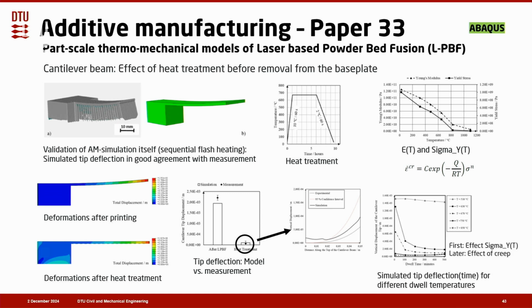So we also made a little DOE, where we simulated the tip deflection as a function of time for different dwell temperatures. Obviously, in the beginning it's the effect of the yield stress as a function of temperature that takes place, that's really governing what goes on. Whereas later on, it's the effect of creep, that's the time-dependent plasticity, kicking in.